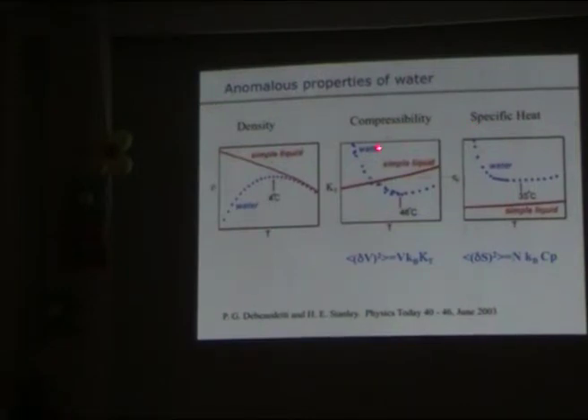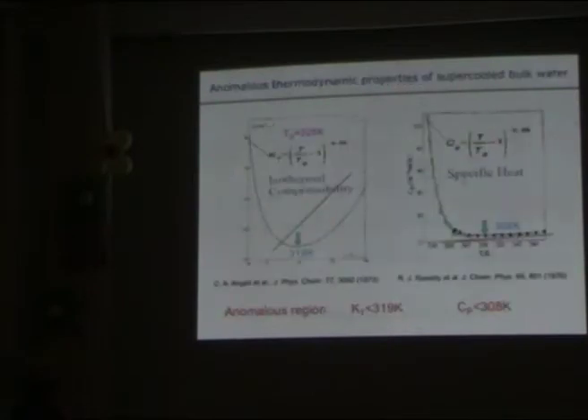There is similar behavior for compressibility. Of course, its minimum is at a different temperature, but you can see the behavior. For a simple liquid, it goes monotonically down as you go to lower temperature, which is consistent with the thermodynamic relations. But for water, it's opposite. Actually, as you go down to even lower temperatures, this anomalous behavior becomes more distinct.